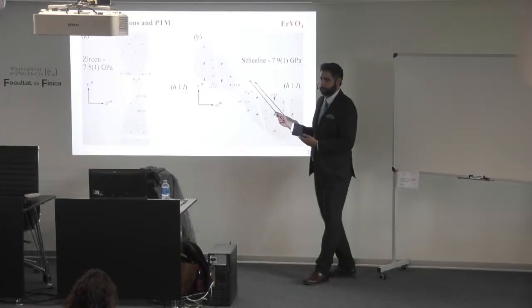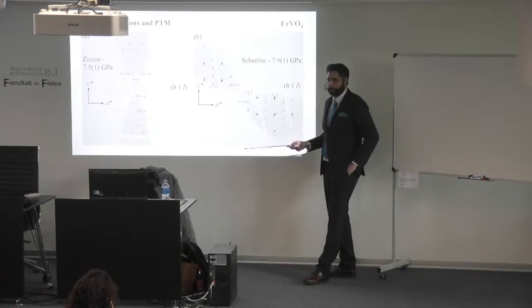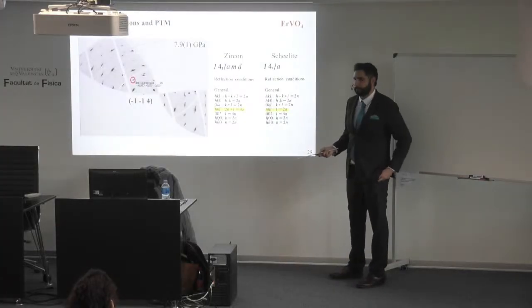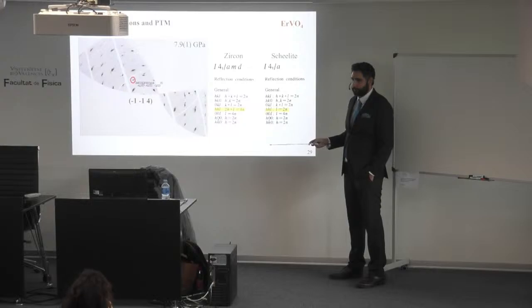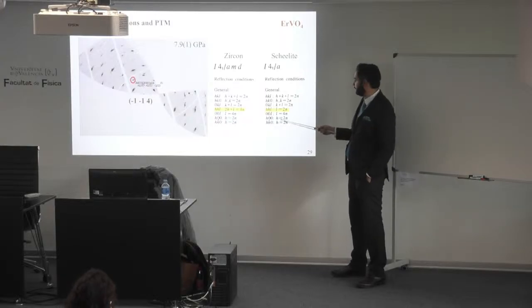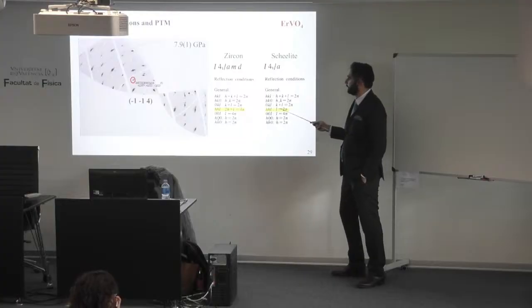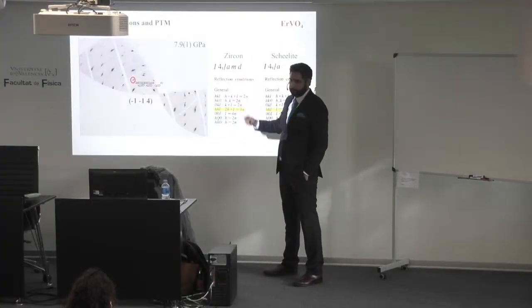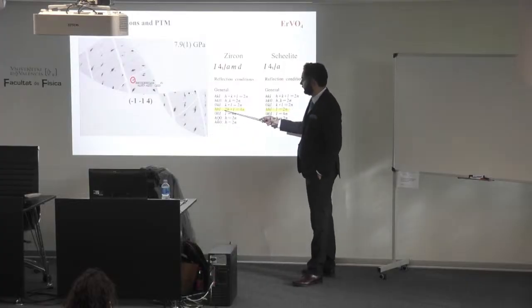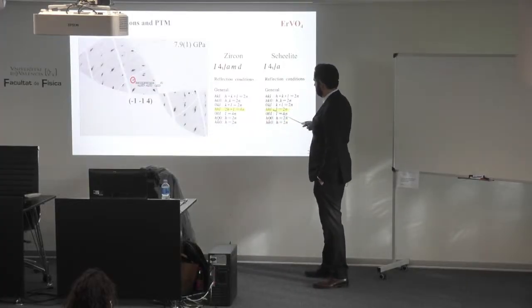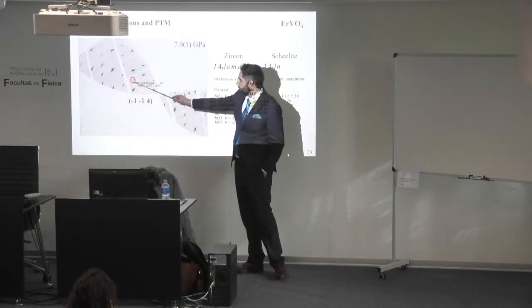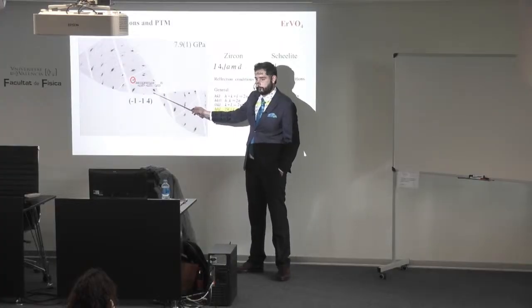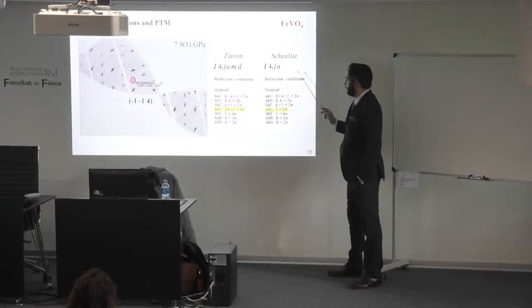But you can ask me, okay, it's different, but are you sure that it is scheelite? Can you confirm it? Well, we can. If we go to selection rules of each structure, the only rule that is different is the one highlighted here, okay? And if we go to a cut in the reciprocal space that has this relation, like the two first ones are the same and the last one is different, this reflection is the -1, -1, 4. Okay? So, if it is scheelite, it should be the last one, even.